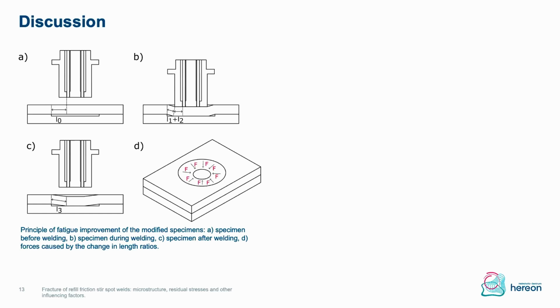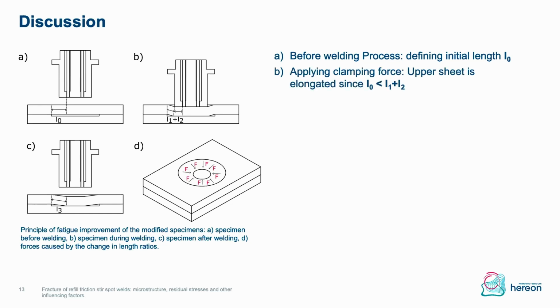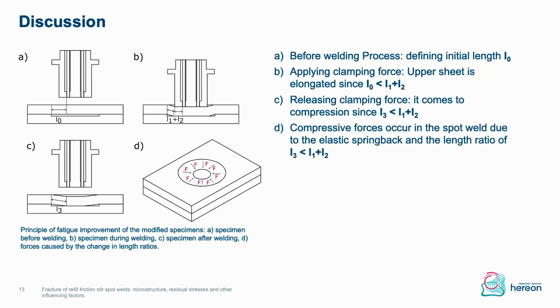But what happened to influence the stresses? Here on the left-hand side, you see the welding process again. With the first picture before the welding process, we defined the initial lengths as you see here. When we then apply the clamping force, the upper sheet is going to be elongated, since L1 and L2 is longer than the initial length. When we release the clamping force, it comes to compression, since L3 is shorter than L1 plus L2. And this results in compressive forces occurring in the spot weld due to the elastic springback and the length ratio, which basically compress the spot weld.